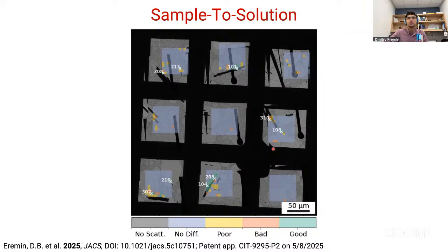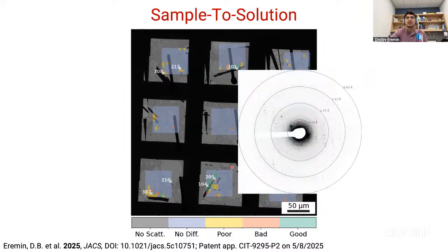And for most of the crystalline materials, I think that reasonably speaking, about 9 to 16 grid squares is actually enough for you to collect some data and maybe even solve the structure right away. So Reyes will select these grid squares for you. Then it will go and map it in diffraction space and create these maps, from which you can see that some of the good diffraction patterns have this very nice organized set of diffraction peaks.